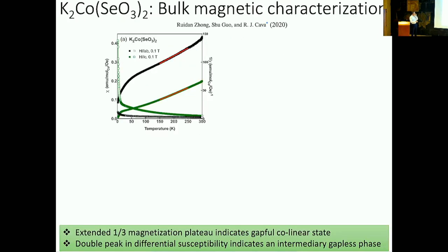All right, so now I'm going to begin to look at the magnetic properties of the materials. And of course, we do specific heat and magnetization measurements. What I'm showing you here is susceptibility as a function of temperature, and I also plotted inverse susceptibility as a function of temperature. We like to look at inverse susceptibility because the extrapolation of the inverse susceptibility to this horizontal axis gives a measure of the strength of the interactions. And when that extrapolation goes to a negative temperature, it indicates an antiferromagnetic interaction. So just this measurement tells us we do have antiferromagnetic interactions as we desired.